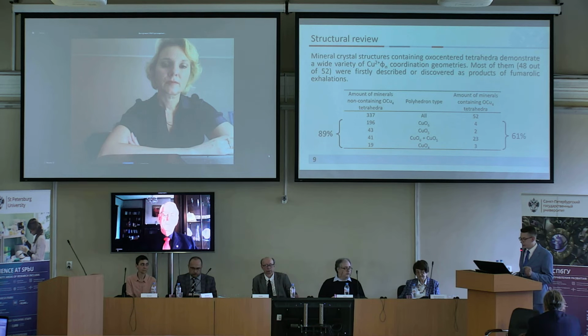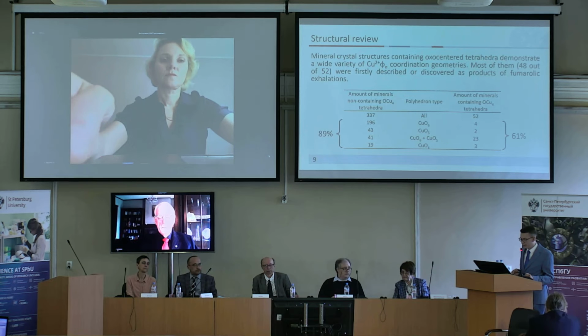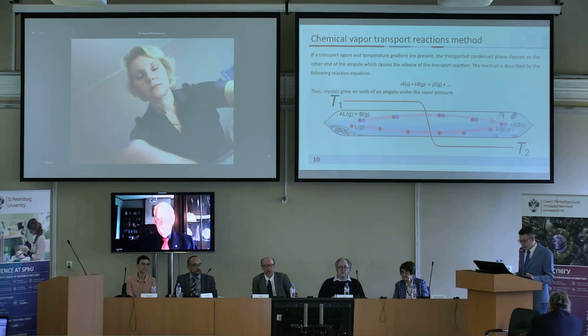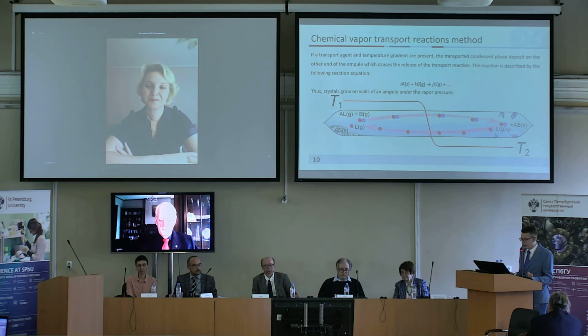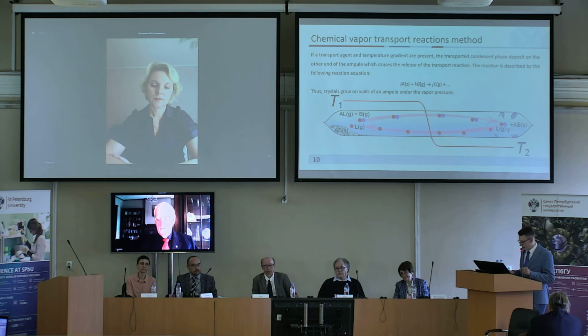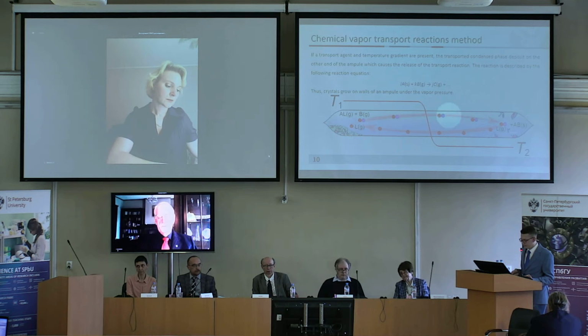Most of the minerals were either first described or discovered as products of volcanic exhalations in fumaroles, which determined the further direction of our experiments. The method of chemical transport reactions was chosen to simulate gas transport in fumaroles. In this method, a mixture of reagents and the transport agent was placed in a quartz ampoule from which air was evacuated, which was then sealed. As the temperature increased, the reaction occurred, and some of the substance was released as gas. And gas transfer to the other end of the ampoule occurred, where the substance precipitates, and then the process is repeated.